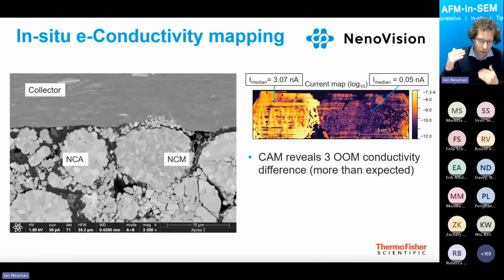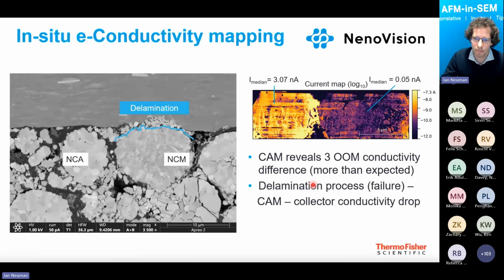Once we presented this result to the experts, they immediately realized that probably something else is also playing a role to explain such a difference, which is a delamination and evident crack in this area, which is actually another important topic. The problem is the delamination of the cathode materials from the collector, which means the conductivity is falling, which means the performance of the battery is going down. So these kinds of measurements can be directly used for the study of delamination processes also.